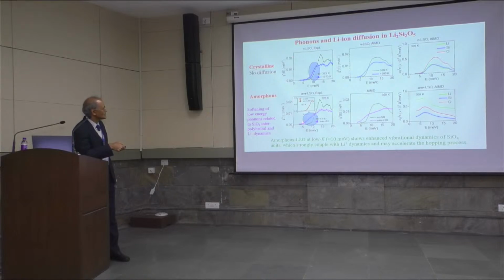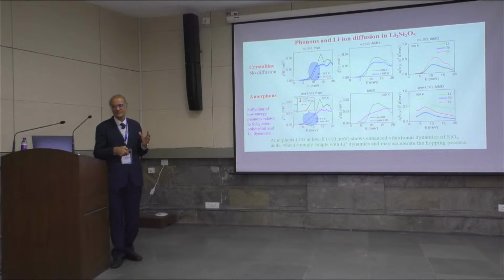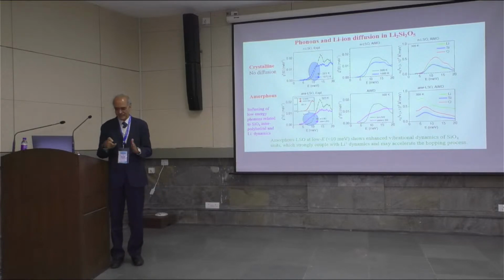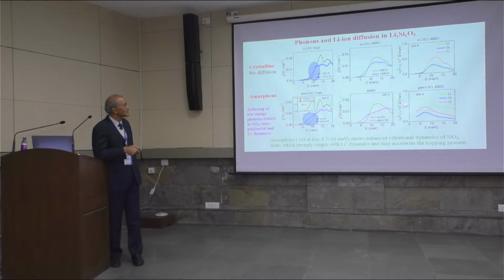Now, if you go to the amorphous structure, then there is a lot more shift and a broadening. So, qualitatively, one can associate this with the softening of these low energy phonons, and we can find out from theoretical calculations what is involved in these phonons. What kind of atomic dynamics or atomic motions are involved. So, through the theoretical calculations, for example, the mean square displacements due to phonons have these components.